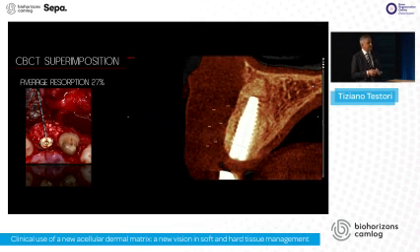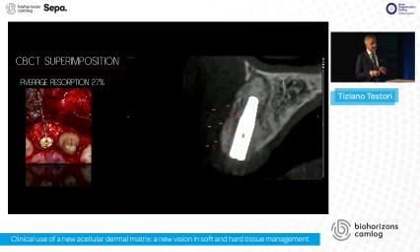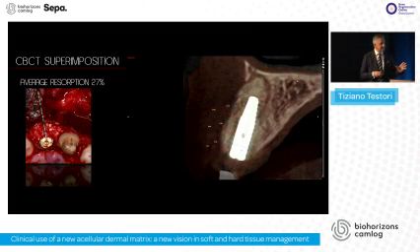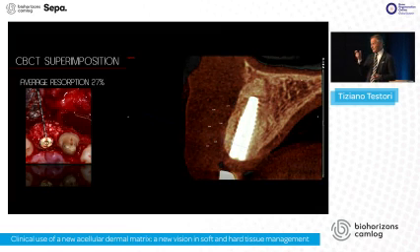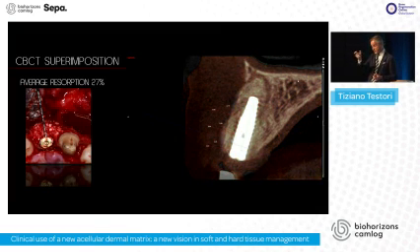And we have an average resorption of this biomaterial of 27% in our cases, with a standard deviation of 11, but at least we achieved the goal of having at least 2 millimeters of thick tissue over our implants on the buccal side.